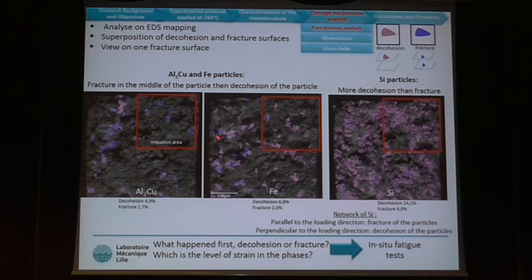So for the Al2Cu and iron particles, it seems to have fracture in the middle of the particle, the blue one, and after decohesion. But for the silicon particles, we see clearly there is more decohesion than fracture, because silicon is a different network, it's like fibers. So when the fibers are parallel to the loading direction, there is fracture of the particles, and when they are perpendicular to the loading direction, we have decohesion, and this decohesion has a higher volume than fracture.